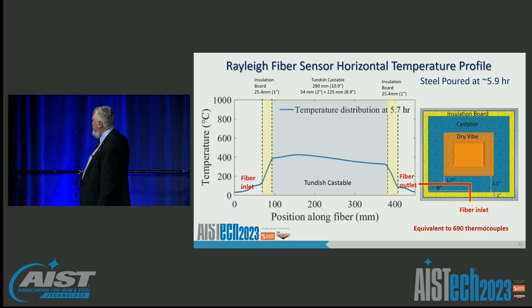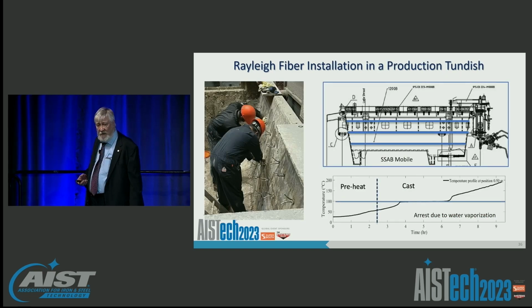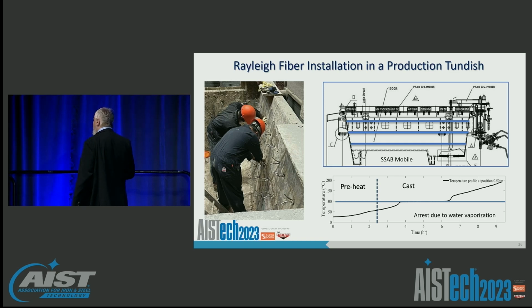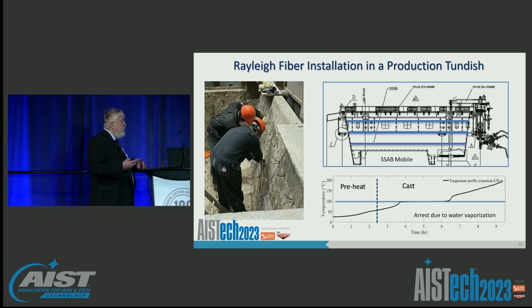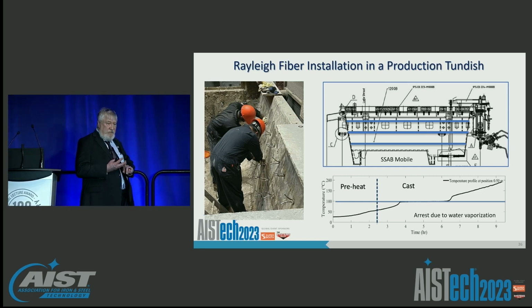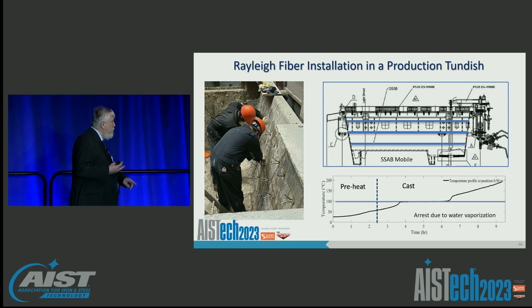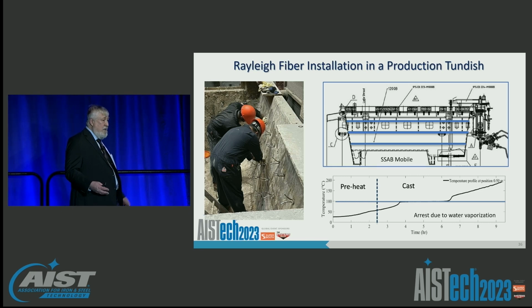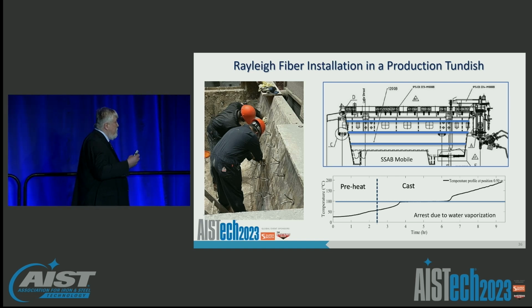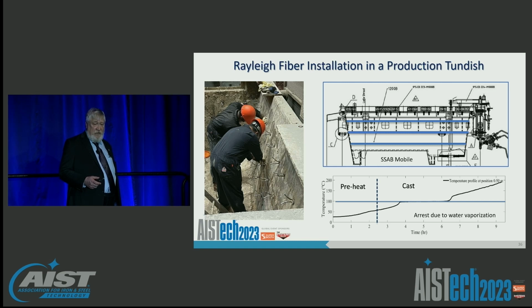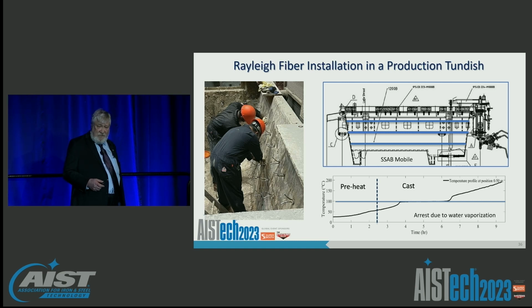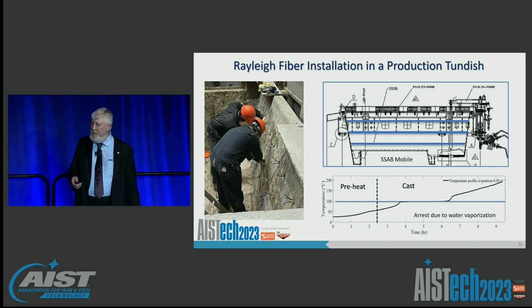So we have also now applied this in plant environments and put them in a commercial tundish. And one of the things we've learned here in this tundish environment is that when spray lining systems are used for both insulating and spray linings, there is a significant delay in the time for which you drive the moisture out of the system. And of course, you can see that thermal profile below and the arrest right around the water evolution from the lining. And it extends well past the preheat period into many, many hours into the cast. This is our high risk for hydrogen pickup, for example. And these types of sensors are really good at sensing those kind of events.